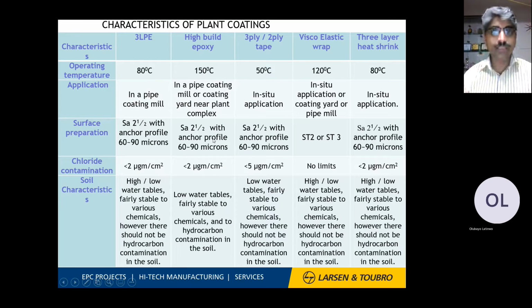This is just a comparison of what we have done so far, based on operating temperature, applications, surface preparations, chloride contamination and soil characteristics. 3LPE is 80 degrees, high build epoxy 150, 3-ply, 2-ply 50, viscoelastic tape 120, and 3-layer heat shrink is up to 80 degrees centigrade, and the other is the surface preparations as listed here.